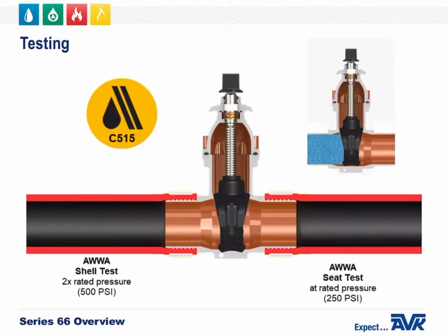The Series 66 gate valves are rated to a working pressure of 250 psi and are tested to AWWA C515, the AWWA standard for reduced wall resilient seat gate valves for water supply service. The pressure testing is performed on the valve before the PE ends are installed. The valve is shell tested to twice the rated working pressure and seat tested at a rated working pressure.